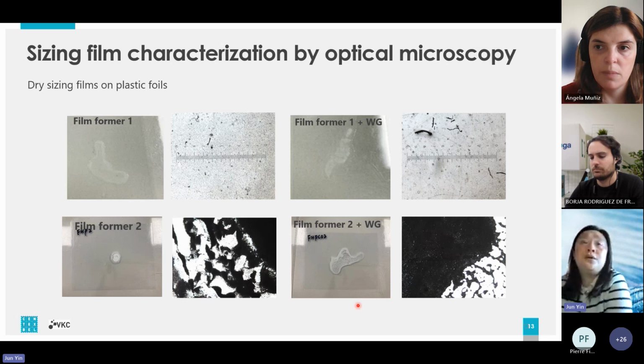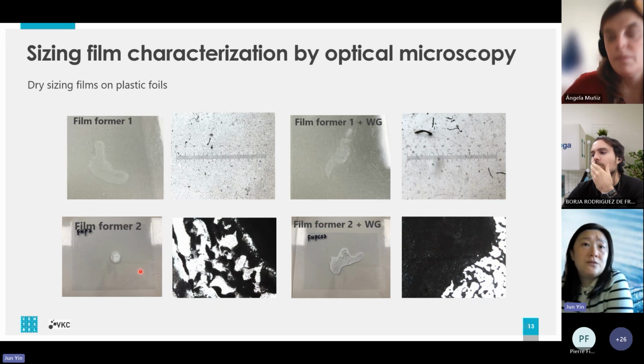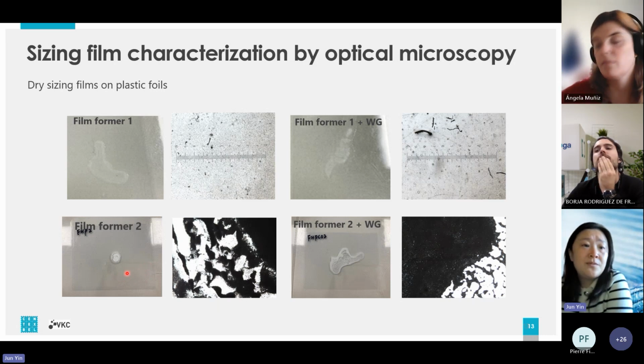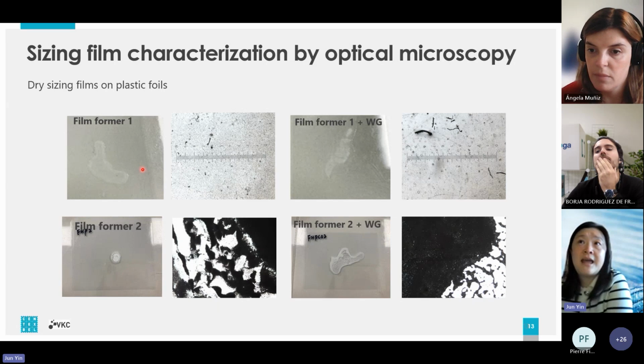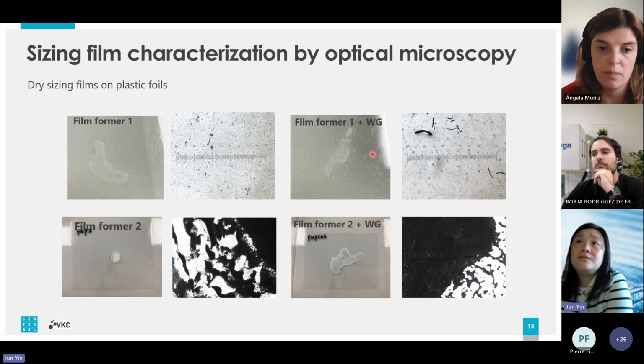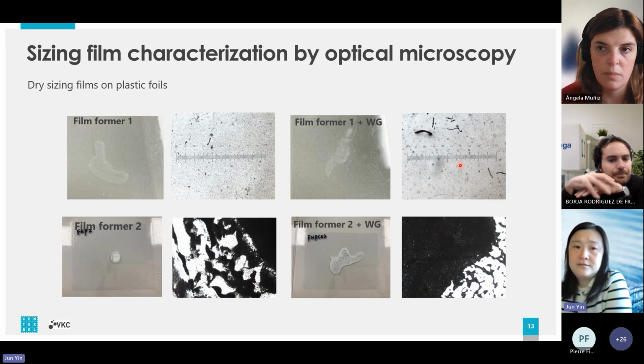So here I show you some examples of film former dried on plastic foils. We can compare film former 1 and film former 2. We can see clearly that film former 2 doesn't have good homogeneous properties. Film former 1 is better. Then we compare the film former with weighting agent or without. We can see by optical microscopy that the film former with weighting agent has a better homogeneity in morphology.